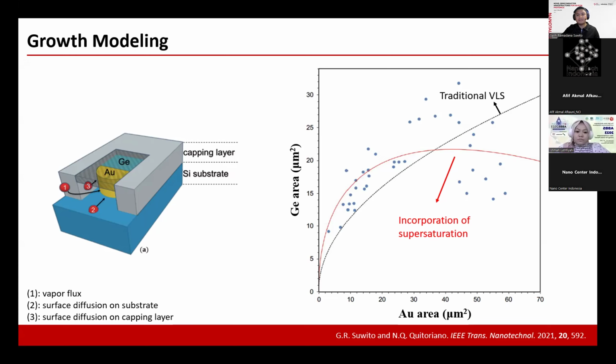The traditional model shown in the black curve in here doesn't give us any peaks, any kind of plateau or peak characteristics. It means that there is something wrong or missing in the way we see the VLS model. It doesn't take into account what we call a supersaturation effect, which needs to vary when you keep increasing your catalyst sizes. So when we try to incorporate this supersaturation effect, shown in the red curve in here, we can reproduce a peak in the kinetics curve.